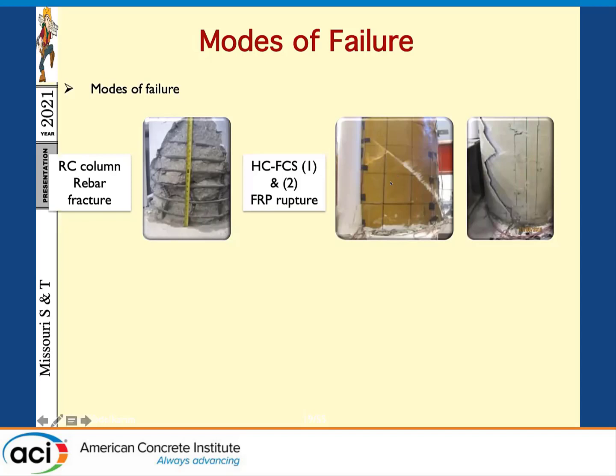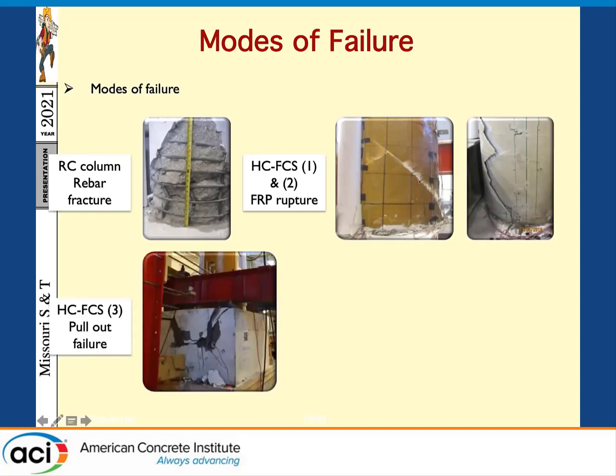To the right over here, the 2 columns: the yellowish one is the epoxy resin FRP, and the one to the far right, the greenish one, is the isopolyester resin with a very thin FRP, 1/8 of an inch. As you see in both of those, we have rupture of the FRP. I forgot to mention that the winding angle for the fiber on those pipes was plus or minus 53 degrees. This is why all the fiber is at a diagonal angle.